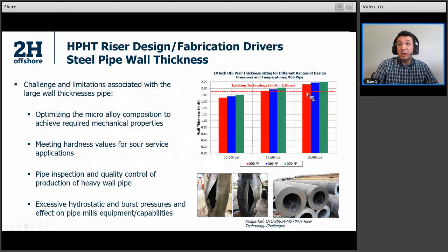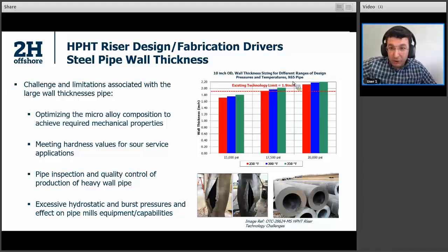In this plot, I am showing the pipe wall thicknesses for the X65 pipe, which is 65 KSI material. If we use X70 pipe, we can of course reduce the pipe wall thicknesses slightly, or with X80 pipe, you can reduce the pipe wall thicknesses further. But again, welding is an issue, hardness is an issue. If you want to use X70 pipe, the welding becomes even more difficult, and meeting the hardness requirement, 250, is even more difficult. As you increase the yield strength of the pipe, you are making your pipe harder, and then your hardness will go up, and meeting the NACE requirements for the sour service region becomes more difficult. So yes, you can reduce the wall thicknesses by using higher grade pipes, but can you weld that higher grade pipe? It is very difficult. So typically, if you look at the operators, they still prefer X65 pipes in the wet tree riser systems.